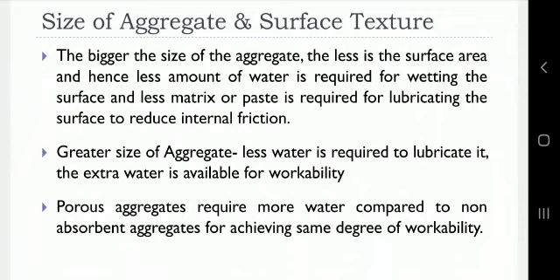Size of aggregate and surface texture. The bigger the size of the aggregate, the less is the surface area, and hence less amount of water is required for wetting the surface, and less matrix or paste is required for lubricating the surface to reduce internal friction. Greater size of aggregate means less water is required to lubricate it, so the extra water is available for workability. Porous aggregates require more water compared to non-absorbent aggregates for achieving the same degree of workability.